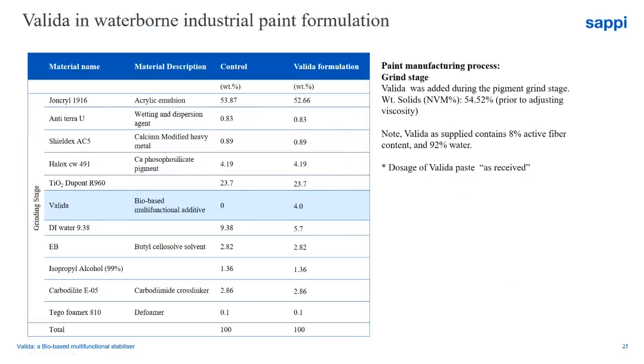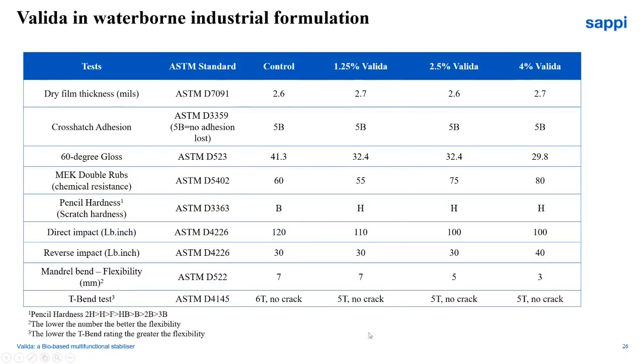The second case study is an industrial coating formulation. Here we added Valida at 4% of the paste grade, again, and we have analyzed different aspects of the coating layer according to ASTM standards, as you can see here. And when adding Valida, we can notice overall better performances, but I would like to focus more on three aspects: the chemical resistance, the scratch hardness, and the flexibility. The chemical resistance of the coating, measured by the MEK double rubs, increased by almost 20% when adding 4% of Valida.